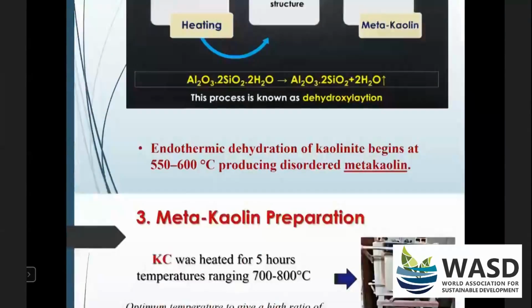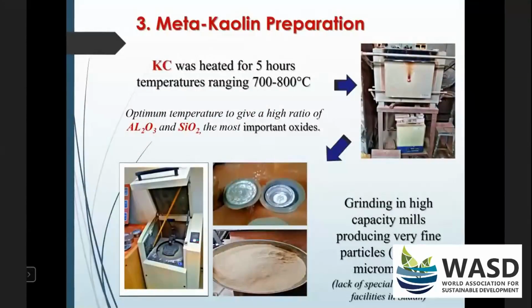For us in the lab, the kaolinite clays were heated for 5 hours at temperatures ranging from 700 to 800 degrees Celsius in a very simple furnace in the lab. After that, the process was followed by grinding it in high capacity mills to produce very fine particles, because basically we are trying to mimic the fineness of cement in our concrete mixtures.